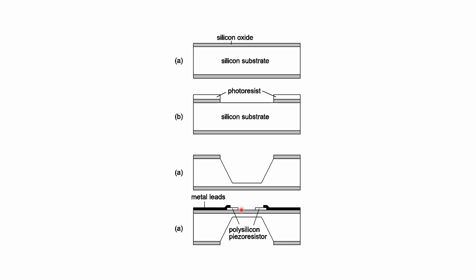And after that, you can deposit, for example, polycrystal silicon on the front side, or you might be able to use doping of a piezoresistor. In either case, this is good for making a pressure sensor. Now, however, this is not a very high yield or robust process. What do we mean by a robust process? A robust process is one that is not sensitive to over etch or timing error.